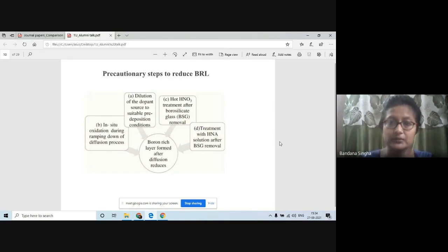Another treatment is used for even higher thicknesses of boron rich layer, that is if it is higher than 38 nanometer or so. This is a treatment for uniform etching of the silicon surface, prepared with nitric acid, acetic acid, and concentrated HF solution taken in the ratio 1:60:6.